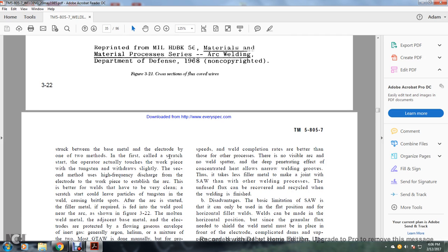There are two methods of starting the arc. The first is called scratch start, in which the operator touches the workpiece with the tungsten and withdraws slightly. The second method usually uses a high frequency discharge from the electrode to the workpiece to establish the arc. This is better because the tungsten and workpiece stay very clean, while scratch start could leave particles of tungsten in the weld, causing a brittle weld after the arc is started.